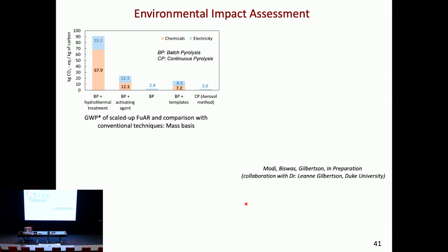So you see the batch processes, the hydrothermal treatment, because of all kinds of activating agents, is significantly higher compared to, let's say, even a batch pyrolysis process without additives and so forth, right? And compared to our aerosol process, it sort of turns out to be one of the best in terms of being a single step, quick residence time turnaround, and so forth.